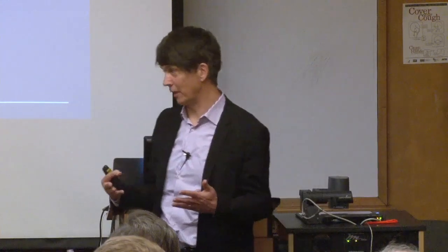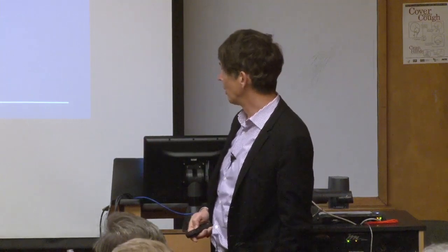And you know, there are people who've claimed that the yield strength of lithium in confinement is 200 megapascal. And I go, well, I've never seen that kind of confinement effect, right? Going from 0.7 to 200. But this is one of these real puzzles in the battery field today. If we don't solve it, we will not use lithium metal, because we have to be able to deal with the mechanics issue of lithium.